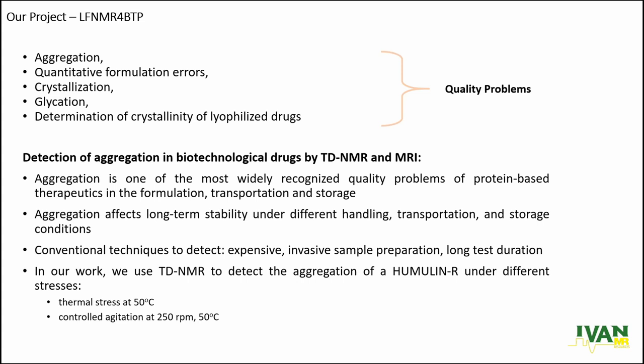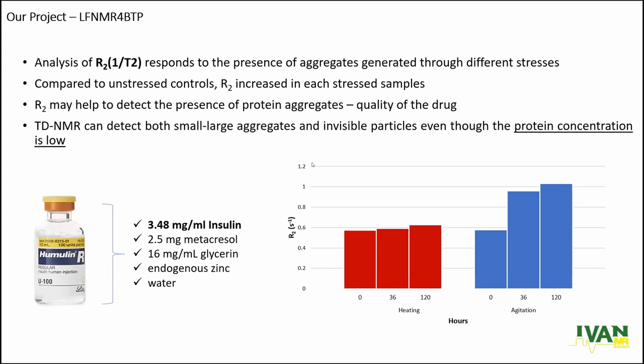Conventional techniques are very expensive, need invasive sample preparation, and have long test durations. In our work, we use TD-NMR to detect aggregation of insulin, which is our model drug, under different stresses. The first one is thermal stress at 50 degrees Celsius, and the second is controlled agitation at 250 RPM at 50 degrees Celsius. These are our preliminary results.